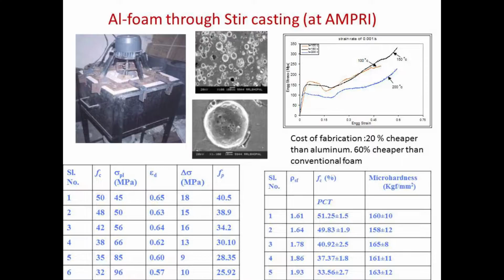But all these additions should be carried out through mechanical stirring. And for better distribution, prior to adding, you can go for a two-step process. First you make the composites, and that composite may go for ultrasonic stirring if the particles are very, very fine. Then after getting that finely distributed composite, you can remelt it and then add the foaming agent. During this time, you should control the temperature. You should have control on the stirring speed, and you should have the facility to take the crucible after foaming and cool it at a very high rate.